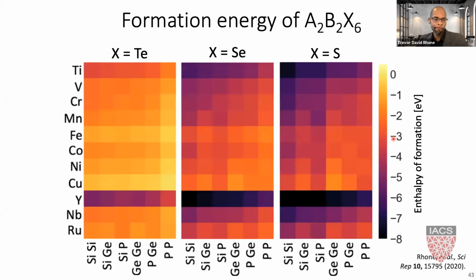So these are the formation energy data. Again, the panels are the X side substitutions, the vertical axis the A side substitutions, and the horizontal axis the B side substitutions. And the color now is formation energy, where the more negative number you are, the darker the square, the more chemically stable you are. And there's a clear trend here, going from left to right in the first row of transition metals, you decrease chemical stability. And if you go along the second row from left to right, you also decrease chemical stability. And so again, I'd like to have a machine learning model learn this pattern and exploit the pattern for quantitative predictions.